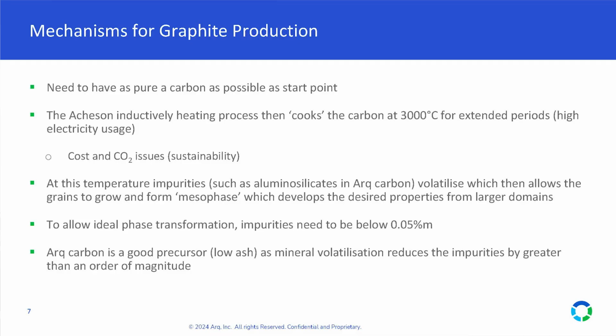So the mechanisms to produce graphite, typically we need to have as pure carbon as possible. So this really relies on our feedstock, which is 99% pure, and we're pushing that to be higher in purity. The Acheson process heats, or cooks, the carbon at 3,000 degrees for extended periods. It's a consumer of electricity, as we all know, and obviously there's CO2 and sustainability elements that are affiliated with this. But at this temperature, when considering the Arq material for this process, some of the 1% impurities, which are predominantly alumina silicates, volatilize, which allows the grains to grow, the mesophase, and continue in the annealing process to form the desired larger domains. Now, to allow for ideal phase transformation, we need impurities to be 0.05% and below.